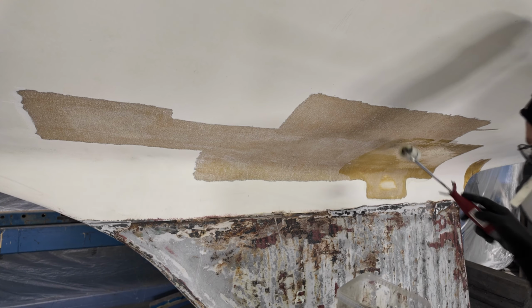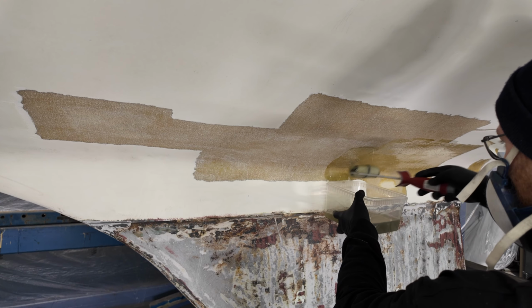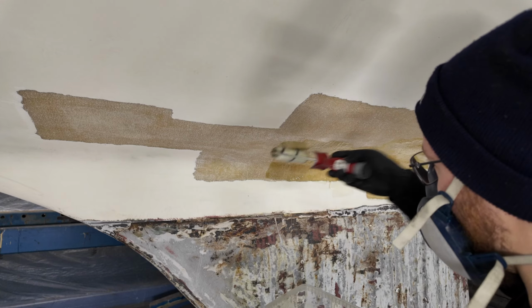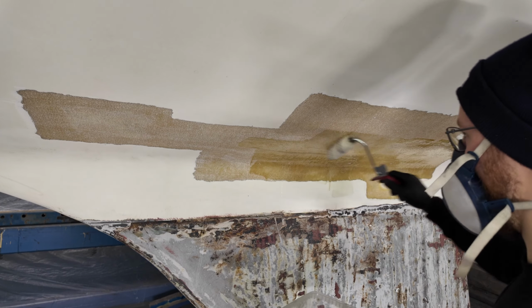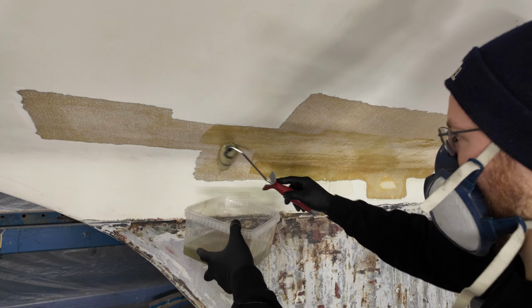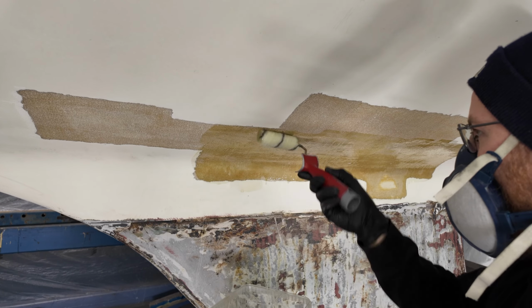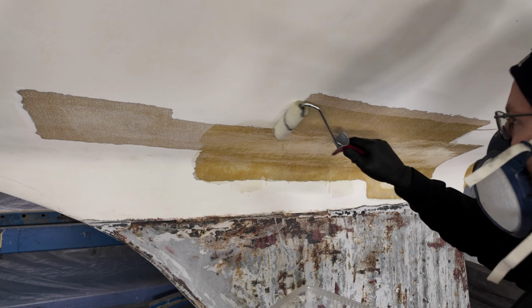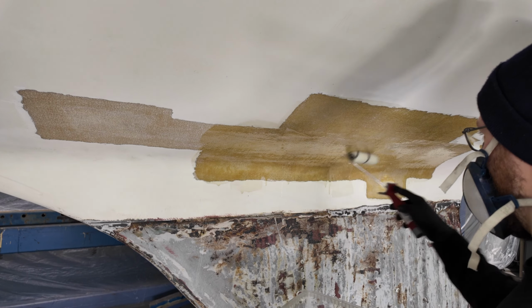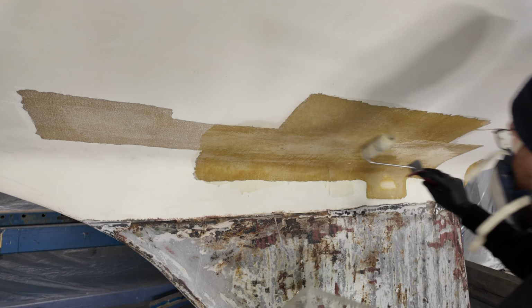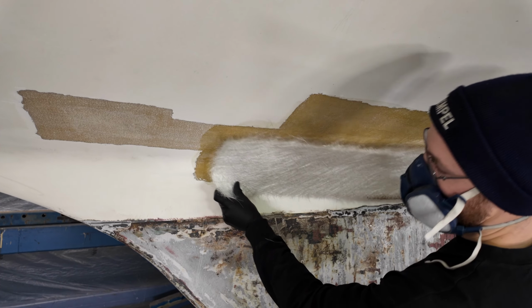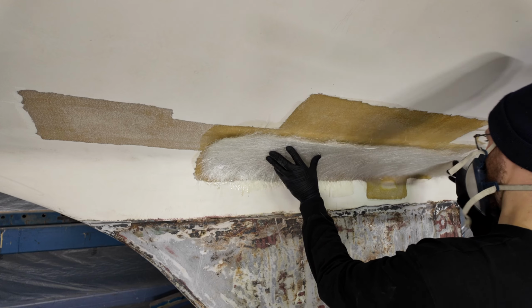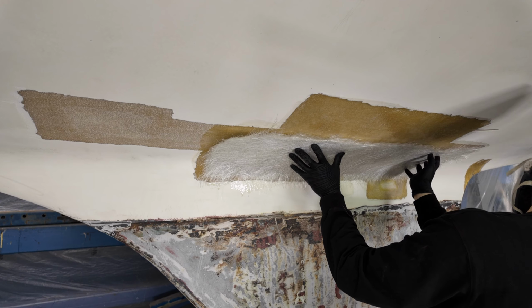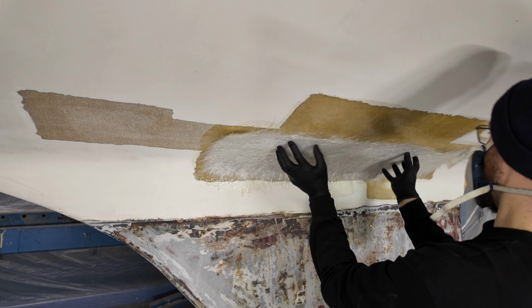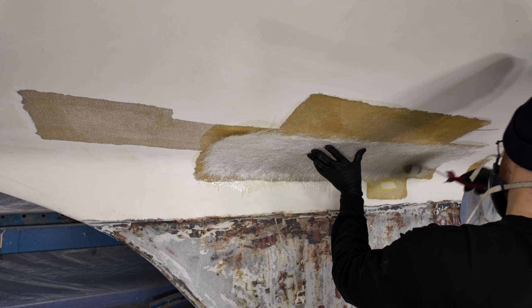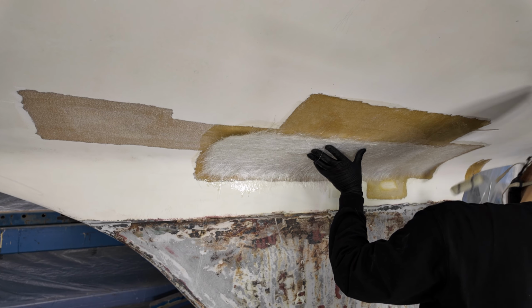I will laminate 3 layers of fiberglass. 2 layers of chopped strand mat, with a layer of diagonally woven fiberglass cloth in between. My reasoning behind it is as follows. First, although not necessary, I wanted at least one layer of woven fiberglass to help spreading the load in this large area. Second, I find woven fiberglass quite awkward to laminate directly onto a hard and uneven surface, and the layer of chopped mat helps a lot with that.